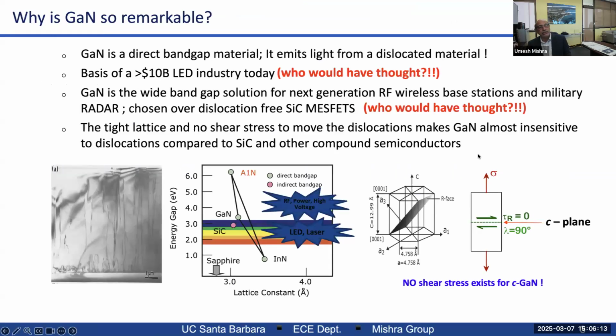So why is GaN so remarkable? It's a direct bandgap material. It emits light from a dislocated material. This is very unusual. No other semiconductor puts out light from a dislocated material. Nobody would have thought that it would be part of a $10 billion, $30 billion now industry. And GaN is a wide bandgap solution. When we started doing GaN, we basically had to fight this myth that silicon carbide was better than GaN because it had a dislocation-free substrate, and we had to say that it really didn't matter, and it didn't.